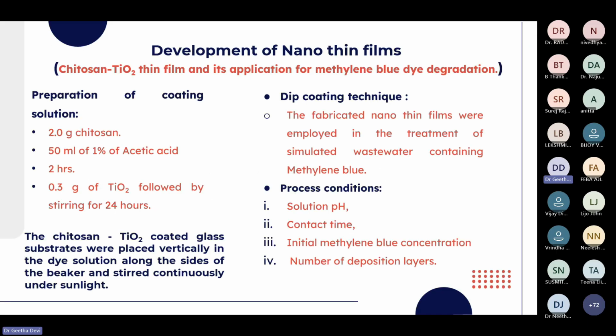And we have employed these nanoparticles in the preparation of nano thin films. So we have prepared chitosan titanium dioxide nano thin films, and they were applied for the degradation of methylene blue dye. For preparing the nano thin films, the coating solution was prepared by mixing 2 grams of chitosan and 50 ml of 1% acetic acid, and the stirring was continued for 2 hours, and then titanium dioxide was added. 0.3 grams of titanium dioxide was slowly added, followed by stirring for 24 hours till it got the required consistency, and that solution was used for the deposition of